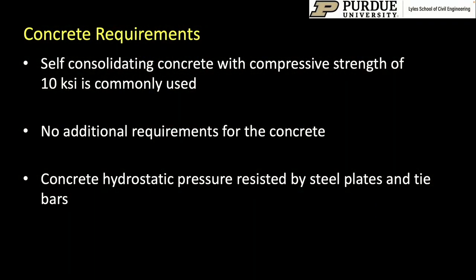So we talked about the requirements for the steel plate, the minimum reinforcement ratio, the maximum reinforcement ratio. We looked at the requirements for the tie bars and also for the shear studs that are applicable before concrete casting and after concrete has been cast. Finally, looking at some of the requirements for the concrete, we usually, in the design of this kind of a speed core system, use self-consolidating concrete with compressive strengths of about 10 KSI. This is commonly being used for most of the applications. There are no additional requirements for the concrete, and the concrete hydrostatic pressure when the concrete is cast is resisted by the steel plates and the tie bars. So this puts together all the detailing requirements for the system that consists of only four simple elements: the steel plates, the tie bars, the shear studs, which are optional, and the concrete infill.